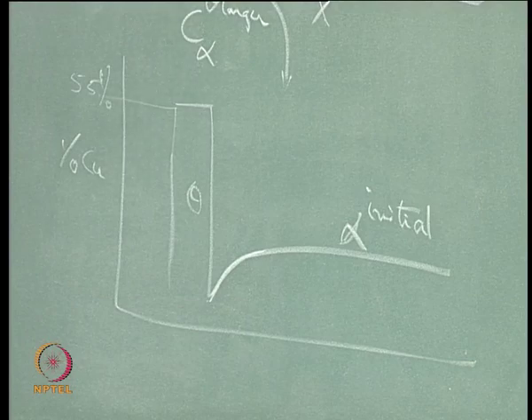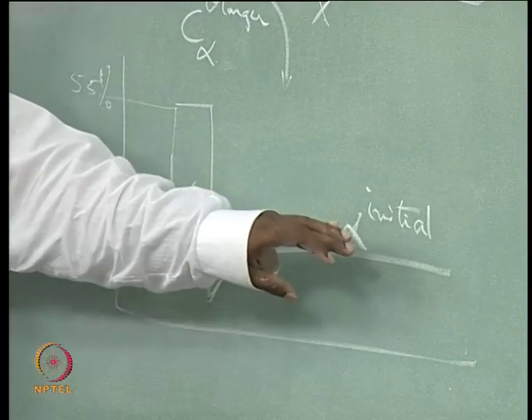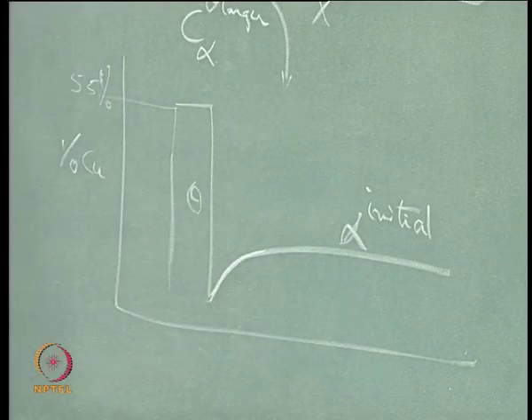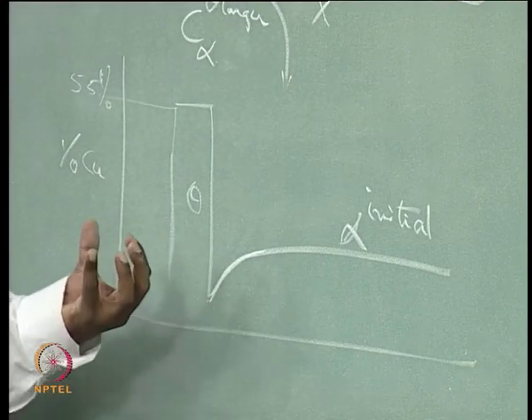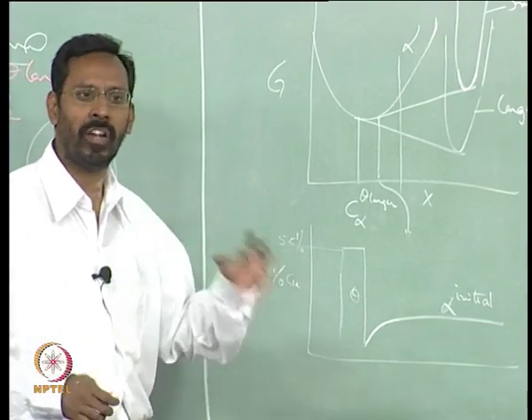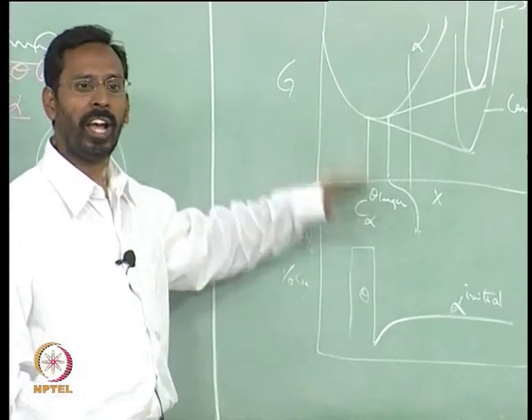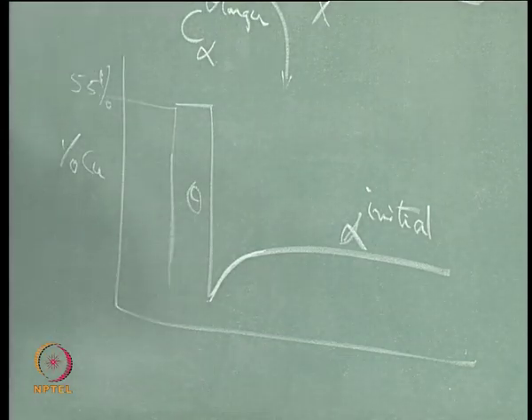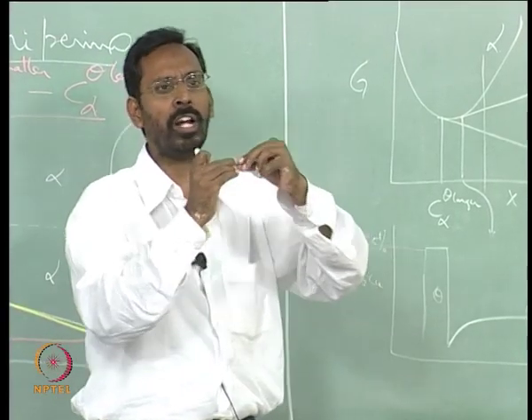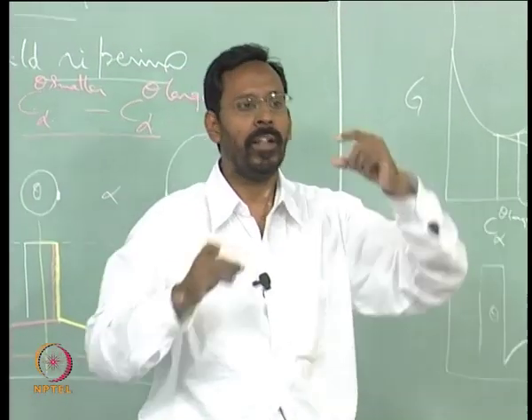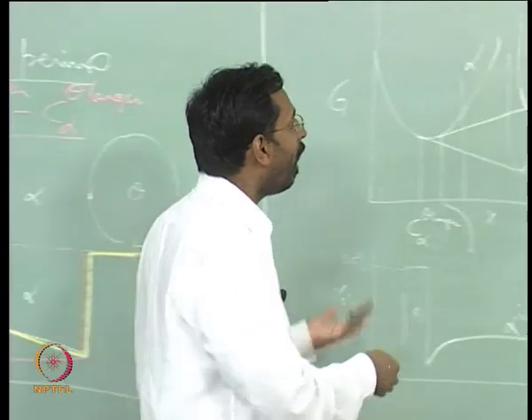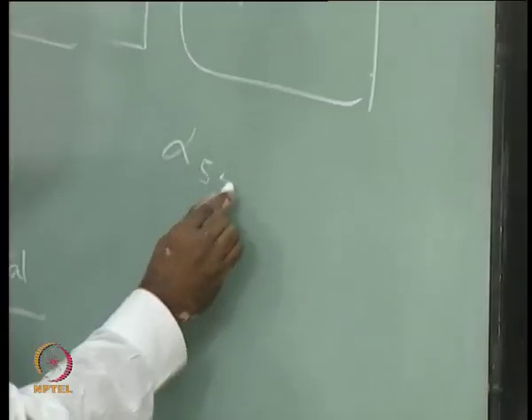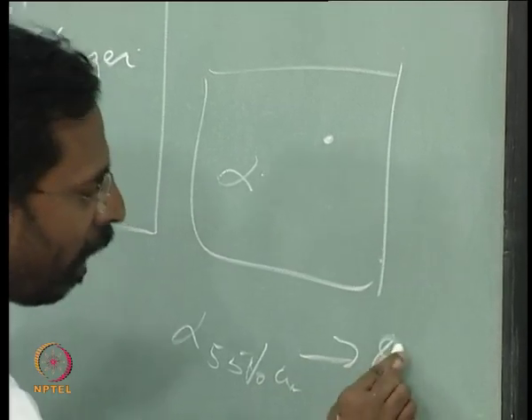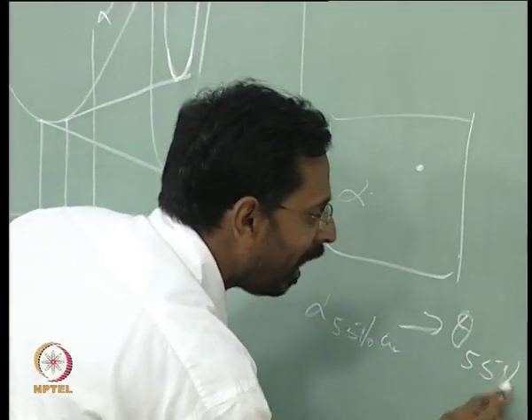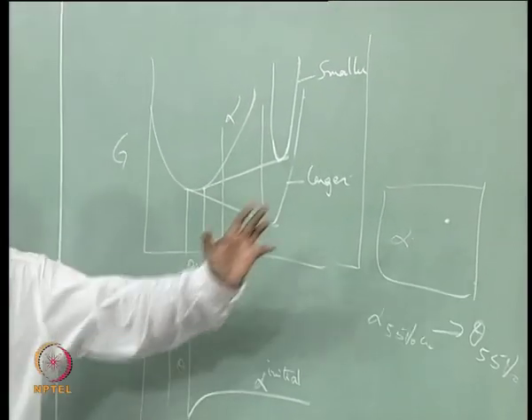and because of the gradient, this copper which is there in alpha starts moving towards the interface, and once it starts moving towards the interface, some copper atoms get accumulated there, and once the amount of the copper atoms is sufficient for the theta, because theta is 55%. So, as the copper atoms keep coming towards theta, once in a small region the copper atoms reach 55%, that small region gets converted. Now, it is almost like alpha of 55% copper gets converted to theta of 55% copper. It is almost like a polymorphous transformation, allotropic transformation kind of.